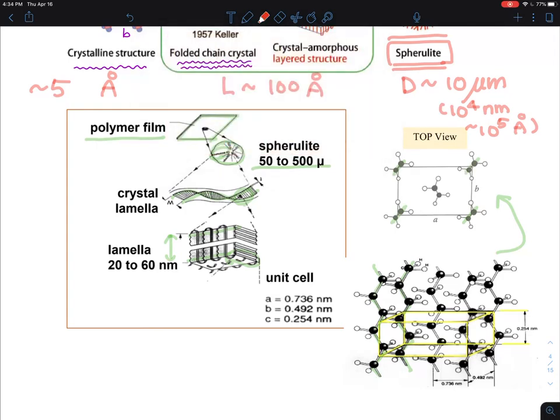And then what they call the herringbone pattern, perpendicular to that, there is another CH2 chain that's going back and forth, filling it up. So this is how they fill up the spaces. The distance between the first one is called A. And the distance between this is called B.